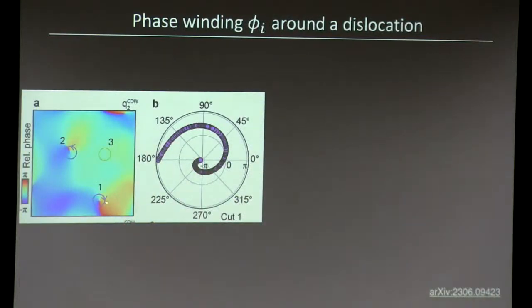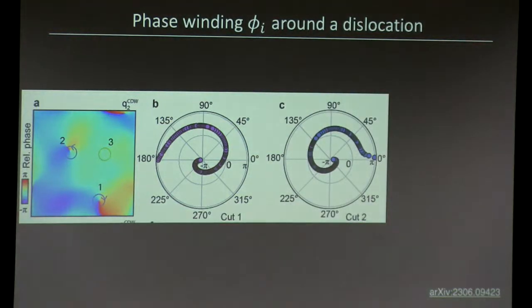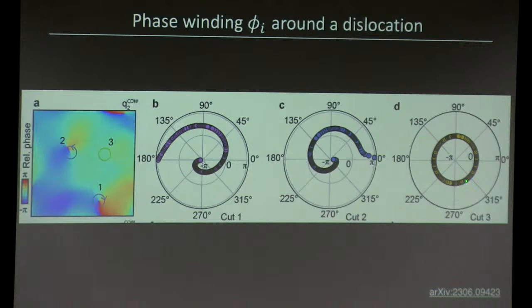We can plot the phase as a function of position. For this one, as you go around this dislocation, you can see that the phase winds by 2 pi in a spiral fashion. This is data, by the way, not theory, around this particular dislocation. Similarly, pick another dislocation right here - you can see the phase is now winding in the opposite direction by 2 pi. And if you go far away from a dislocation, then the phase just doesn't change at all.